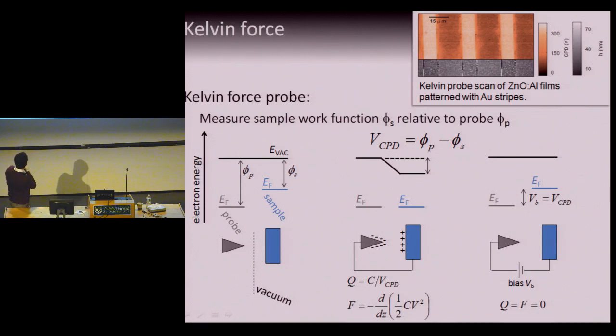This is a similar picture to the one I drew before to illustrate how the formation of an N-type Schottky barrier arises. Here I have a probe, this is a pointy guy, and a sample. They have different work functions, and right now they're separated by vacuum. They're unconnected electrically. Now what I've done is run a wire between the two of them. And as I described before, electrons flow downhill in potential energy space. So you have a net flow of electrons from the low work function material to the high work function material. And we have drawn here a transfer of electrons from the sample to the probe. The technique works the other way around, but just for concreteness, I wanted to illustrate in one direction.